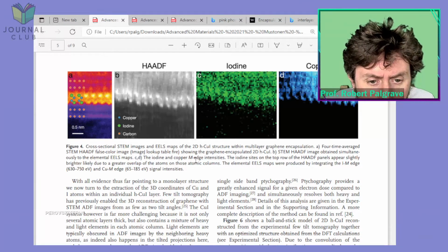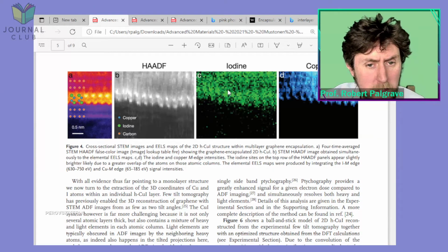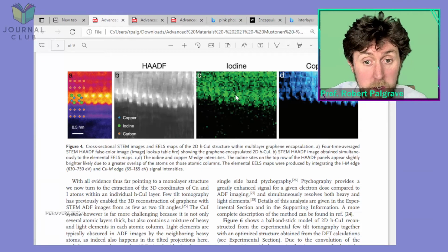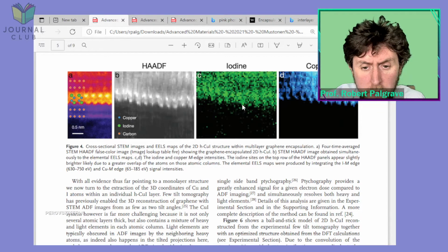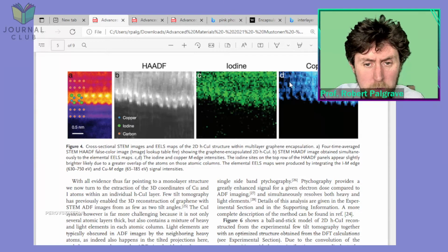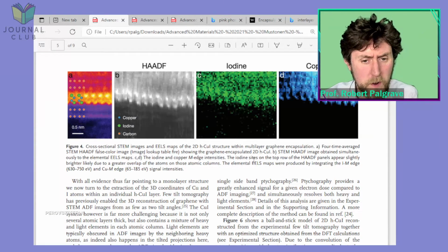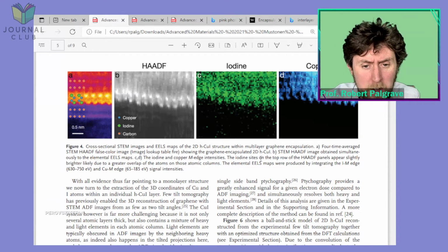The iodine and copper M edge intensity. So this should be, again, showing you the locations of the iodine and copper. But it seems like the iodine is kind of everywhere and the copper is kind of everywhere above the layer. So I don't fully understand that. The iodine sites on the top row of the HAADF panels appear slightly brighter, due to greater overlap of the atoms on those atomic columns.